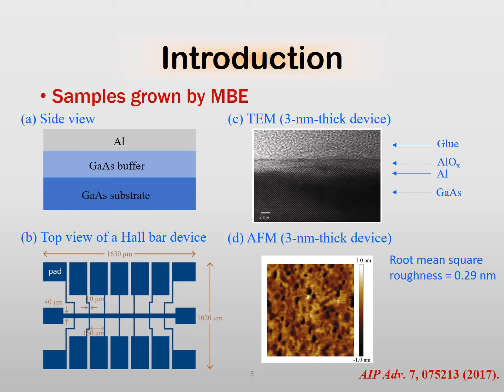All the samples were grown on a Gallium Arsenide substrate by MBE. We needed to grow a Gallium Arsenide buffer layer before growing an aluminum nanofilm. The grown film thickness ranges from 3 nanometers to 4 nanometers. As you can see in the TEM image, aluminum does get oxidized on the surface. This oxide layer prevents the aluminum nanofilm from further oxidation.